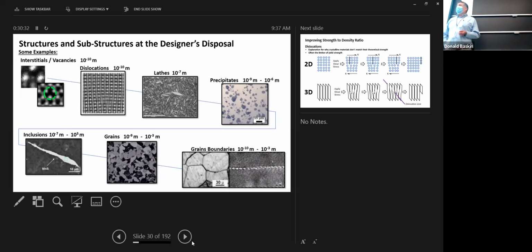There's inclusions. I always say to people that sulfur sunk the Titanic, right? When they made the Titanic, the material specs weren't that clean back then, and the steel sometimes had a lot of sulfur in it. Sulfur combines with manganese to form manganese sulfide stringers. These can be highly detrimental to the toughness of the material. I've actually seen micrographs. I have a book at home with micrographs of the steel from the Titanic, and it was full of sulfur stringers.